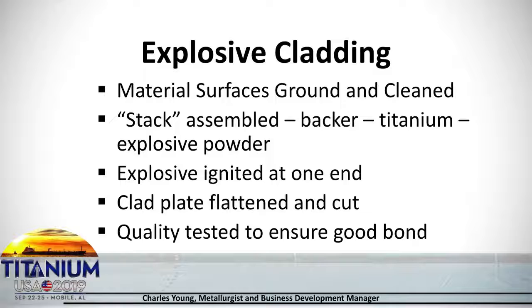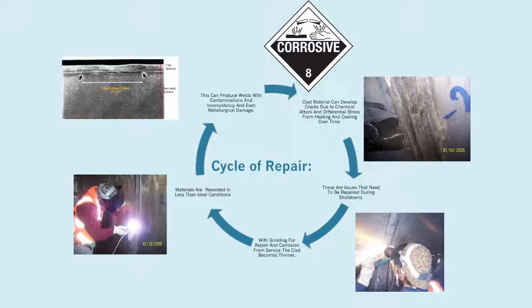But these explosive bonded vessels always have some issues because they're subject to some corrosion. They're also subject to heating and cooling cycles. So they end up getting some cracks, some areas where they may need repaired. And as you repair those, you're going to grind out the cracks, you're going to grind out the corrosive areas, you're going to weld repair those, but every time you grind out that titanium layer, you're going to get thinner. So the question is, how thin can you go before your repair is actually causing more problems than it's solving?